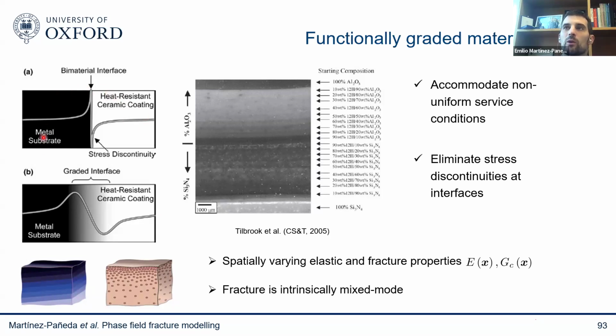So imagine here you have a metal substrate, a ceramic. You want to avoid this kind of bimaterial interface, so you make things smooth by having a graded interface, a material property that changes in composition progressively from 100% metal to 100% ceramic. This is what you see here. You can go from this composition of 100% progressively to 100% of your other material, basically.